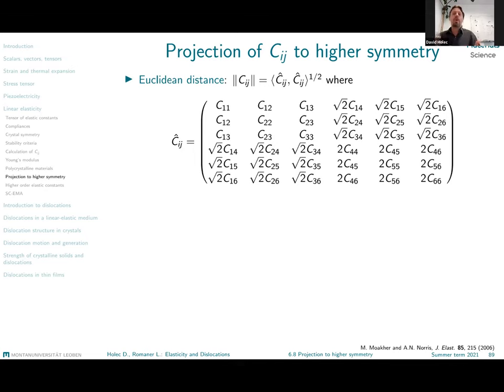But eventually you want to provide for a cubic material just one C11 value, right? You do not want to have C11, C22, C33 and say, well, my material is not perfectly cubic. No, the fact that it is not perfectly cubic is a consequence of numerical inaccuracies. So now out of the result that you obtained, you want to extract values that indeed follow the desired cubic symmetry, but at the same time are as close to the values that you actually calculated as possible.